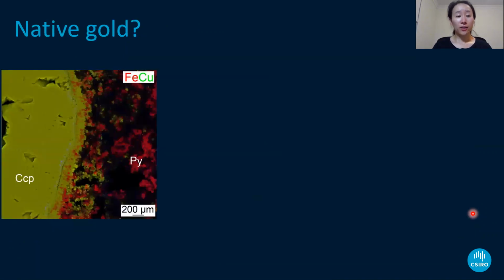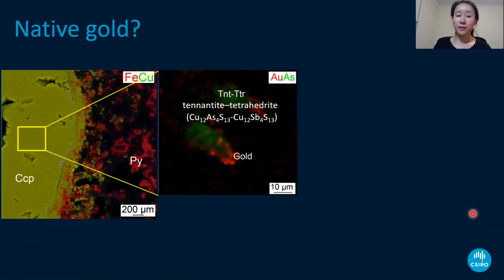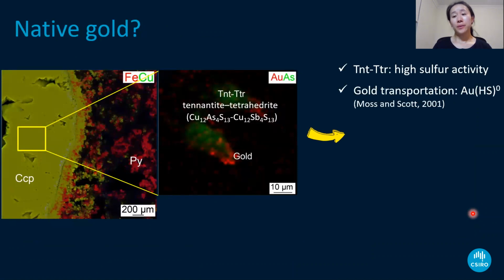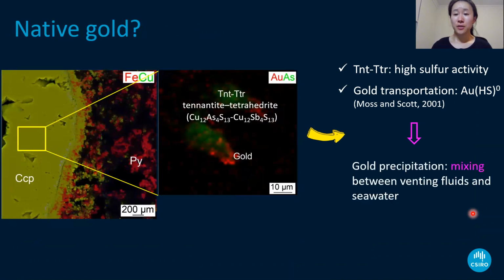Okay, now let's take a look at gold. As I mentioned before, the first type of gold is associated with tennantite and tetrahedrite minerals. The occurrence of these minerals indicates high sulfur activities in the venting fluid. And the gold has also been suggested to be transported as gold bisulfide complexes in the venting fluid. Therefore, gold is likely to precipitate due to the mixing between the venting fluid and the seawater, which will reduce the sulfur activity and drive gold precipitation.